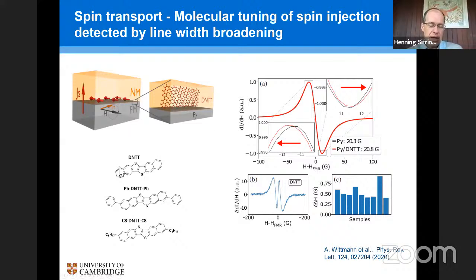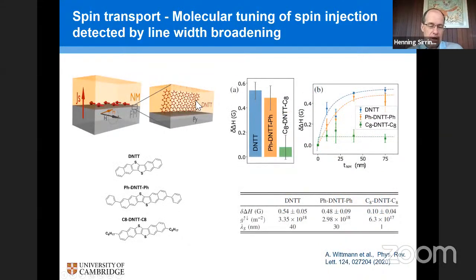You can deposit the neat molecule, and that gives you in fact the largest broadening, because this molecule is then in very close contact with the interface. But if you deposit this alkyl substituted molecule, the alkyl side chains are electronically inactive, they are insulating. If you have such a monolayer of insulating side chains at the interface, that suppresses the spin injection very effectively, and we weren't able to detect any line width broadening in that system. From these measurements, you can do them as a function of thickness, and you can then determine the spin diffusion length in the organic semiconductor, and you get values of a few tens of nanometers. So this is a fundamental interest in understanding also spin transport in these materials.